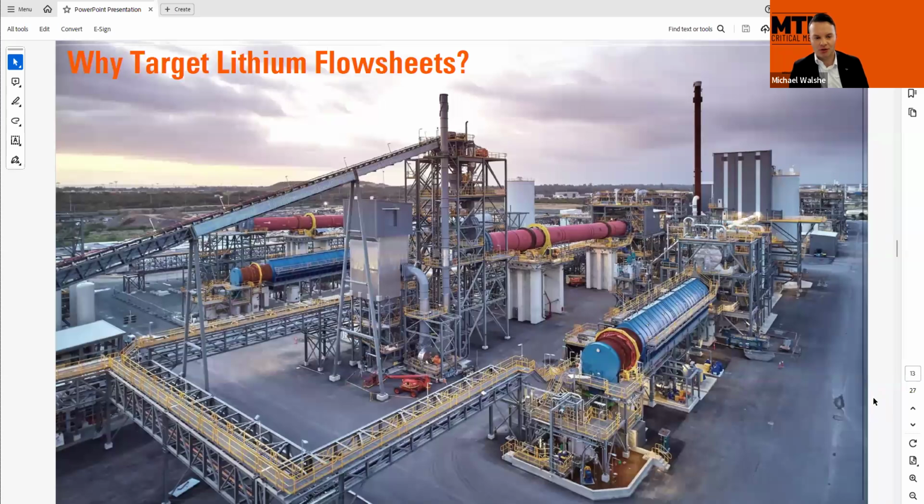The image here shows one of those, and the photo here shows 4 horizontal rotary kilns. Now, what are those kilns for? Well, spodumene is a very refractory mineral, meaning that it's really challenging to extract the lithium from it, because the lithium atom is so tightly bound to the other atoms in the mineral. Even the strongest acid won't dissolve that in its natural state. The technical term for the natural state is called the alpha polymorph.